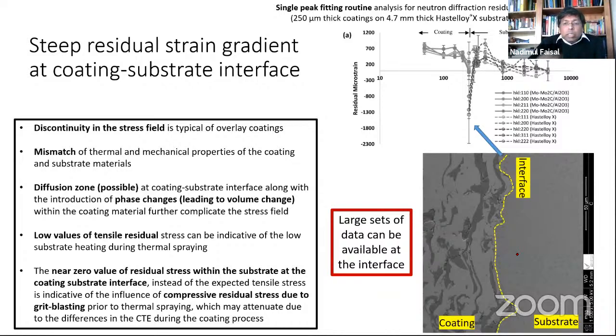Right, so the interface is an important thing to worry about. If you're analyzing within 50 micron on either side of the interface, you have to be very careful. You can expect huge error if you're not analyzing the data carefully. However, a lot of work can be done in this domain, a large set of data of different types can be investigated. In my experience, I would say this is an area which has been very least investigated, at the interface of these coatings. A very steep rise in residual strain gradient can happen.